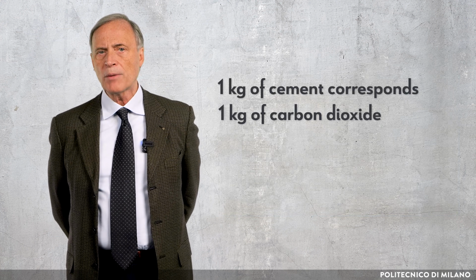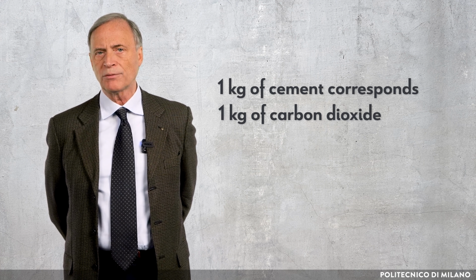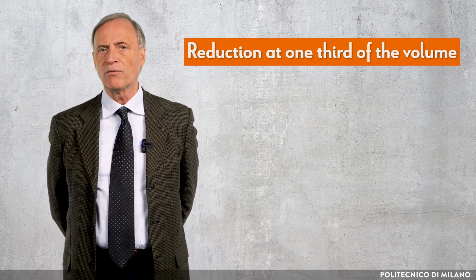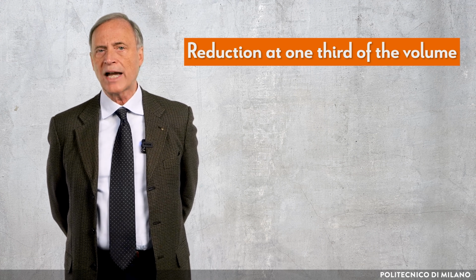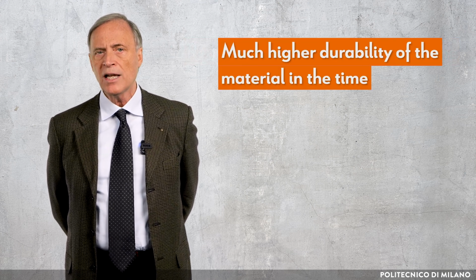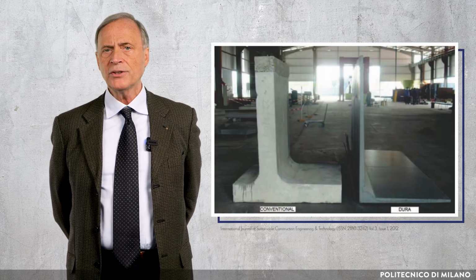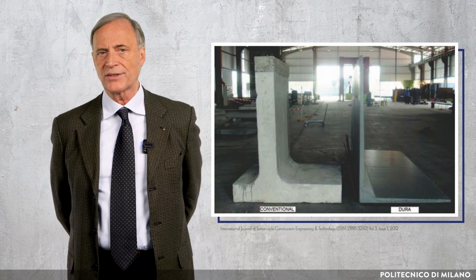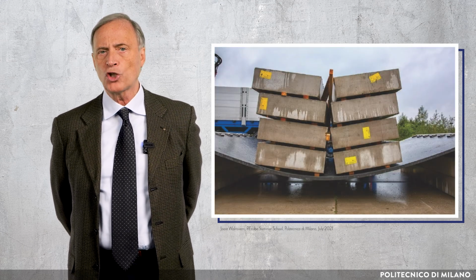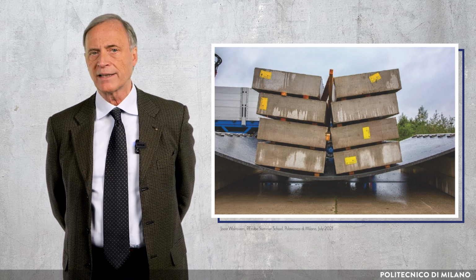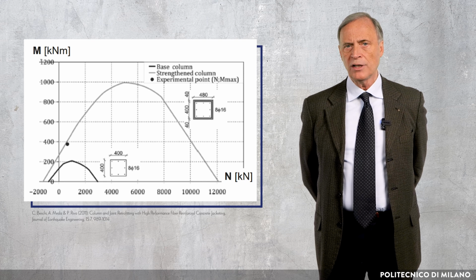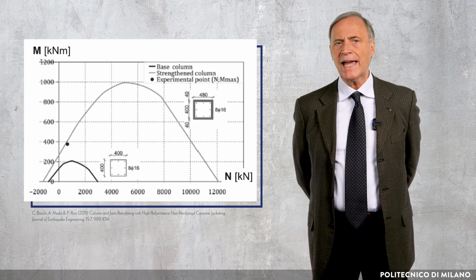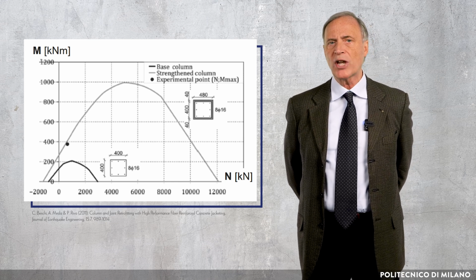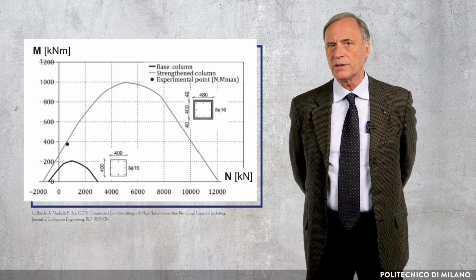We know that 1 kilogram of cement corresponds to around 1 kilogram of CO2 emission in the atmosphere. This means that to obtain a sustainable material, a reduction to 1/3 of the volume needed for a conventional concrete element must be obtained in the structural design when this type of material is adopted. The quality of the surface and the very low porosity guarantee also a much higher durability of the material in time. A comparison in terms of equal bending strength is shown with reference to a wall thickness. An example of bearing capacity in bending is also shown to highlight the impressive resistance of this material before cracking. The high strength in compression and in tension can allow an impressive increase even of the domain M-N, bending moment versus axial force, of a column by using the jacketing technique, represented by a reduced thickness of only 40 mm.